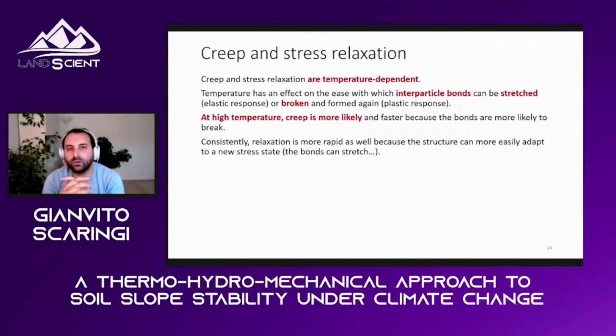And again, we are going in our laboratory to make tests on that, doing a shear creep test in direct shear devices. And key to understand why creep depends on temperature, we need to look again at the microstructure, at the interparticle bonds and the chemical bonds, how they are broken at higher temperature with more ease. And there is consensus that at elevated temperature, creep is more likely and is faster, but relaxation is more rapid.